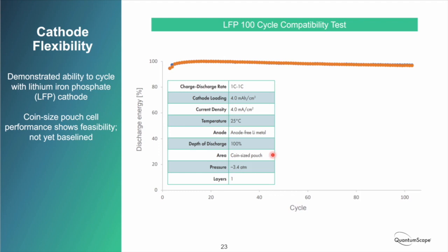The last point I'll make about LFP is, because it's a lower voltage chemistry, for the same loading, it's going to have a thicker cathode and therefore require a thicker anode. So when you are using a hosted anode, that anode will impose a larger penalty on LFP than it would on a high voltage material. So if you switch to our architecture of a lithium metal anode that's anode free, you get an even bigger benefit on LFP than you do on a high voltage cathode. So the energy density improvements that we hope to enable for NMC will be, on a percentage basis, even larger on LFP. So that could be interesting. We'll see how this plays out as we move forward.